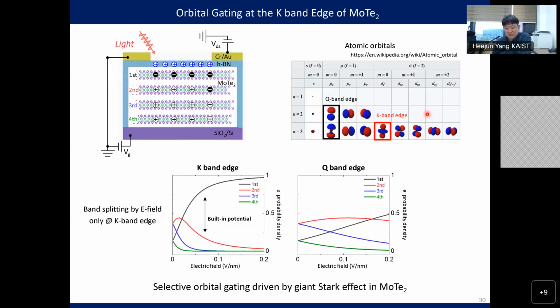So instead of MoS2, somehow we use MoTe2, but the physics is the same. MoS2 and MoTe2, they are 2D semiconductors. And then, as I said, we always have some defects in the hBN layer, and we have some screening. In condensed matter physics, this is called screening. But when you learn Thomas-Fermi screening in a condensed matter course, we assume electrons are not interacting with each other, and we have a screening length, the Debye length. But here, depending on the orbital nature inside the MoTe2, K-valley electrons and Q-valley electrons have different interaction between atomic layers. So we cannot freely apply Thomas-Fermi screening theory here.